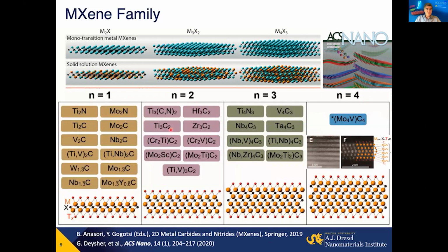produced already. And earlier this year, we published in ACS Nano, in the January issue, an article showing that it's possible to add also structures with 5 layers of transition metal and 4 layers of carbon, making, for example, this carbide, molybdenum 4 vanadium C4, with a herringbone layer structure. And this is certainly far from the end. Moreover, about 100 simple stoichiometric MXenes are possible. With solid solutions possible on both sides, the number of materials in this system is virtually infinite. And it's still not the end.